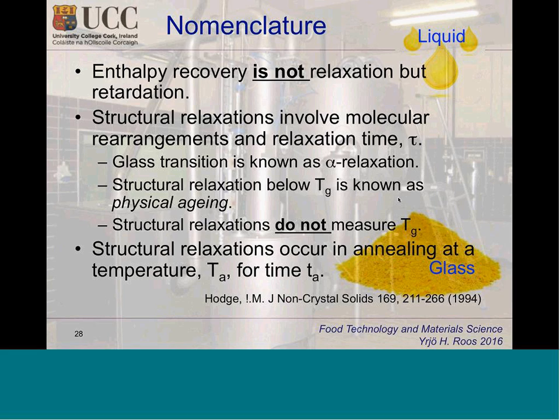Then structural relaxation involves the molecular rearrangement, so we are measuring how fast those happen, and we have the relaxation time parameter to look at that. That's what we can measure with mechanical spectroscopy or dielectric spectroscopy or the dynamic methods that I showed before. Relaxation, in fact, is the phenomenon that happens. Transition is the cause of the phenomenon, and the glass transition is the thermodynamic event that we can follow using the expansion coefficient or the heat capacity and those types of parameters.